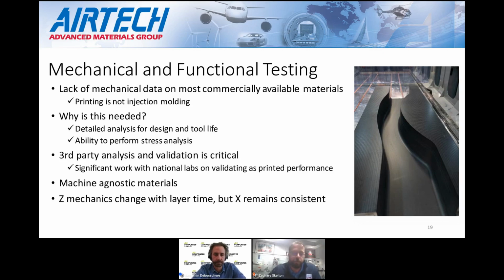So we've done a significant amount of work with the national labs here in the US, as well as in Europe, validating the as-printed performance. But again, making sure our materials are machine agnostic, that we can work on any print platform. And then understanding how those Z mechanics change as a function of layer time. So typically the bead stacking will drop off as you push the layer times longer and longer. The X values will remain fairly consistent. As you go and print larger and larger, sometimes you don't have a choice, and you need to understand if the tool is going to meet the intended use, if we are pushing that layer time longer and longer.